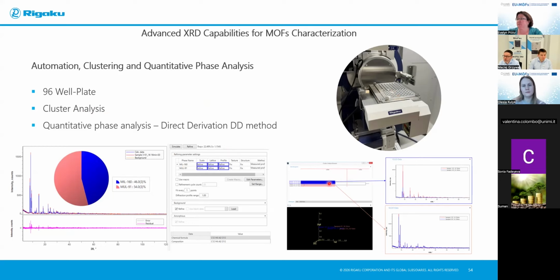At the same time, we can group the powder patterns based on the similarity, and as well, we can perform quantitative phase analysis. Rigaku developed a special method, which is called direct derivation method. This is a patented method for quantitative phase analysis in case we don't have a crystal model. Like you know, probably for Rietveld refinement, if we want to use Rietveld analysis for quantitative phase analysis, we always need to have a crystal model, but sometimes we have unknown compounds, unknown phases, and this type of analysis is not possible. In such a case, we apply the direct derivation method for crystalline and amorphous phases, and based on the measured powder pattern for the single phase and information about the composition of the phase, we can perform a quantitative phase analysis.